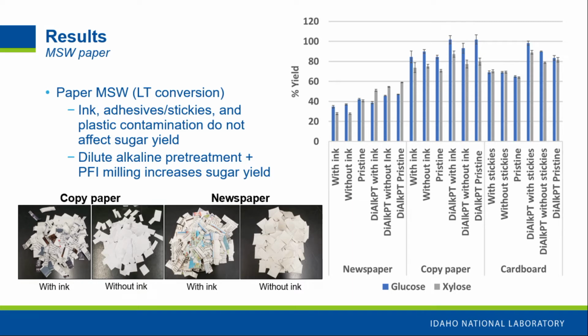But in our low temperature conversion tests for our mixed paper, we basically sorted out anything with ink, stickies, or any sort of plastic contamination. And we wanted to see how this would impact our enzymatic hydrolysis yields. And we found that those contaminants did not actually really impact them at all. But what did impact our yields is we used a dilute alkaline pretreatment and mechanical refining method, and found that by using this method that's commonly used for lignocellulosic biomass, we were able to increase yields. So we are calling it a decontamination method, but it's something that would actually be done during conversion at like a biorefinery.